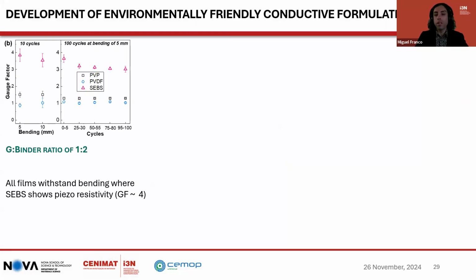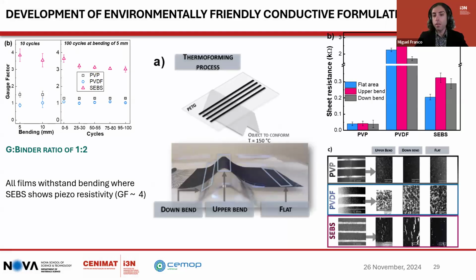To test its mechanical properties, all films were subjected to bending tests. All the formulations withstand 100 cycles at a bending radius of 5 millimeters, and SEBS shows piezoresistivity with a gauge factor of 4. Also, thermoforming was tested as a proof of concept for conformable electronics. PETG was used as a substrate, and after conformation only PVP withstood without an increase of sheet resistance. Surprisingly, SEBS, as an elastomer, showed an increase of resistance due to the presence of microcracks after conformation.